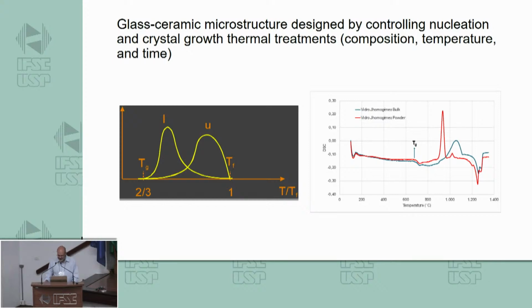To give you some reference, if we make a DSC, or a thermal analysis characterization of a glass, in the heating we find the Tg as a change in the baseline in the endothermic direction, and the glass can or cannot crystallize in the time of the thermal analysis. If it crystallizes, we see the crystallization peak, maybe another one, depending on the composition, and then the melting. And the end point of the melting marks the liquidus, more or less. It's an estimate of the liquidus of this system.